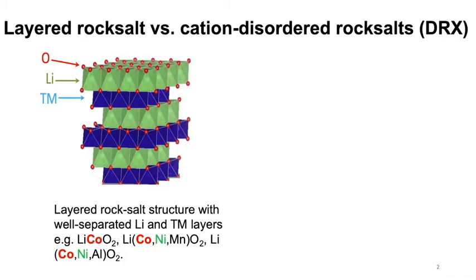During the past 15 to 20 years, the research on lithium-ion cathodes has been dominated by the so-called layered rocksalt structure, as shown in this figure. The layered rocksalt structure has separated lithium layers and transition metal layers, and the lithium migration happens along these 2D lithium layers.